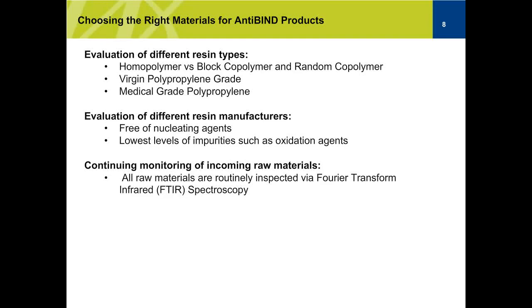Now, polypropylene, right? Not all polypropylene is alike. Not everything is the same. And what we have found is that the amount of leachables in solution is directly correlated to the impurities in the starting materials, the starting resin. So we took a lot of effort and a lot of time to make sure that we start with the right material. So we evaluate the different resin types.